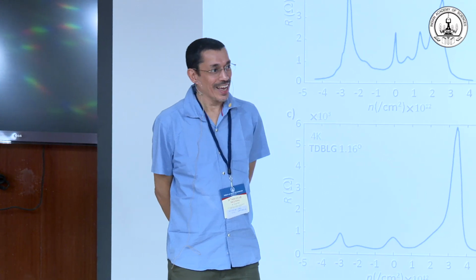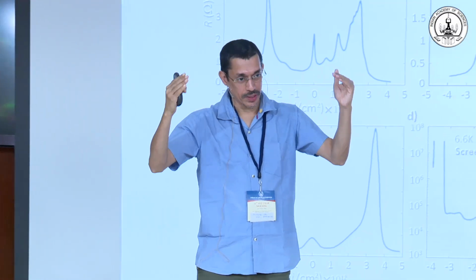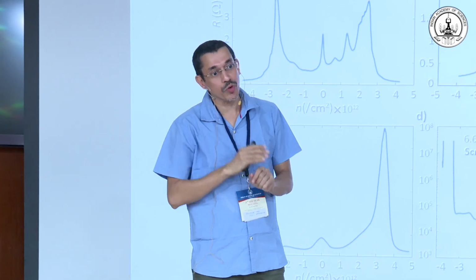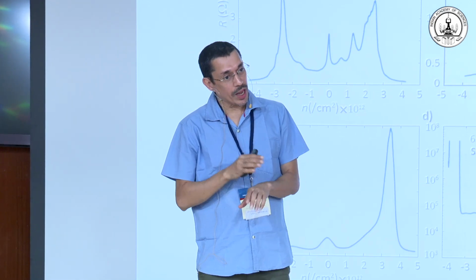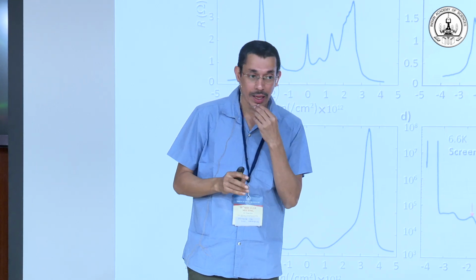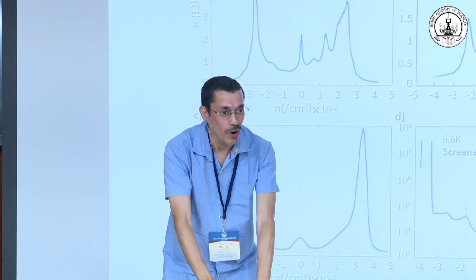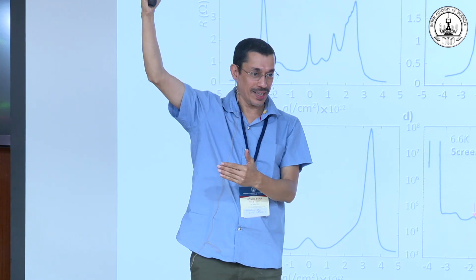Anindya, this is a follow-up of what Sankalpa asked. Is it that after you anneal the sample, because you do some annealing after you've done the twisting, right? No, we don't. In fact, we avoid heating. Then why does your device become stable? No, because heating means above room temperature, right? Usually the pick-up and everything is close to room temperature. We never go even to 50 degrees centigrade. You mentioned thermal cycles mean going from low temperature to room temperature, not above room temperature. Okay.